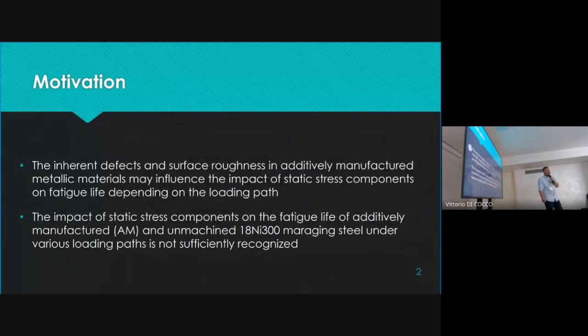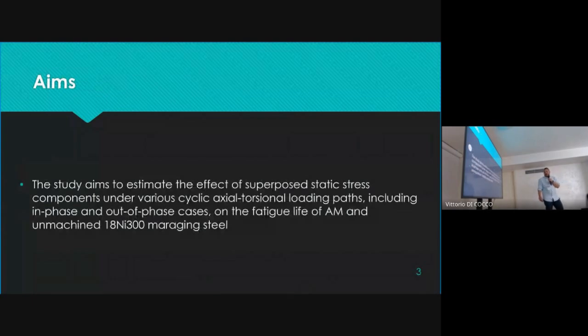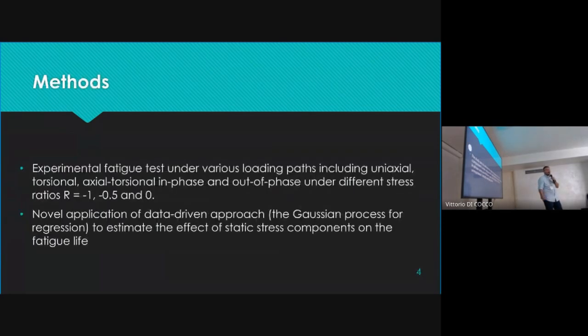So we decided to take this approach, and our study aims to estimate the effect of the superimposed static stresses, the mean values, under various cyclic axial-torsional loadings, including the in-phase and out-of-phase loadings of the additively manufactured maraging steel. Our fatigue experiments were done under various loading paths, 22 to be exact, for axial and torsional in-phase and out-of-phase stresses with stress ratio -1, -0.5, and 0. And then we use a novel application of a data-driven approach, Gaussian process regression, to estimate the effect of the static stress component on the fatigue life.